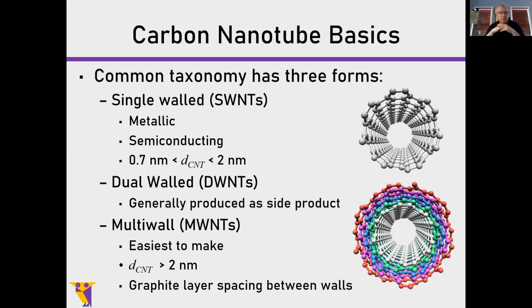They generally come in 2 forms, metallic and semiconducting. And that property is determined really by, for want of a better term, the degree of twist around the bond axis. There are indices associated with this. Certain combinations of indices yield metallic conduction versus non-metallic or semiconducting. They generally have diameters between 0.7 of a nanometer and about 2 nanometers.